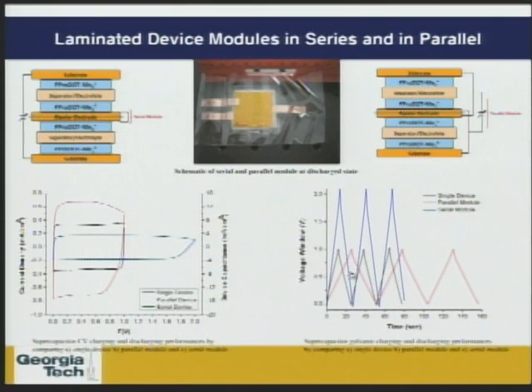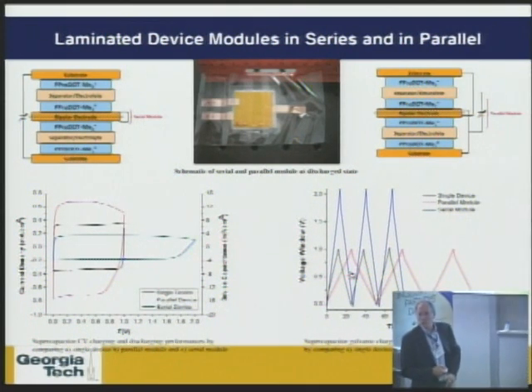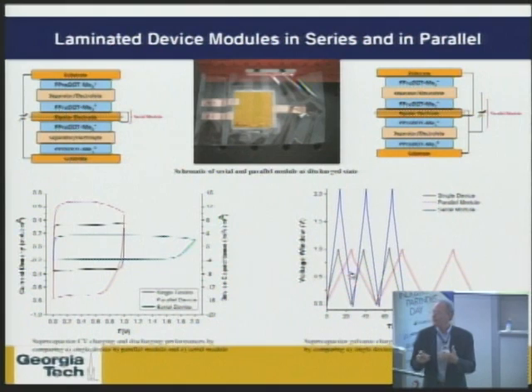Now, since they're flexible and flat electrodes, we can bring these together and we can stack them. And you can see the word I've used for this in the past is that of a Dagwood sandwich. If you imagine bringing lots of layers together, in essence stacking multiple capacitors together with a bipolar electrode bringing these two together. And in essence what this allows us to do then is to combine these flat capacitors into modules. And so if you look at the capacitance here in black of a single device, you see that we have on the order of 8 millifarads per square centimeter with a cell that's operating out to almost 1 volt.